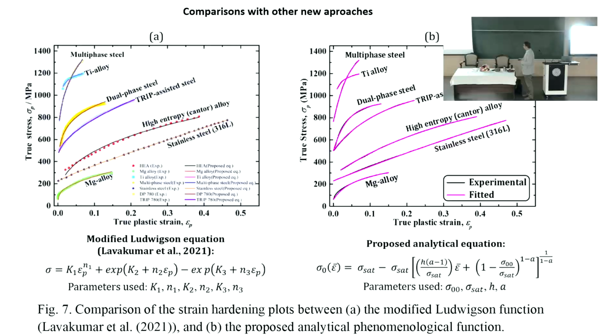You see, here is the function, 1, 2, 3, 4, 6 parameters. 6. We have 4. And one of them is not really a parameter. Let's say 3 and a half. So we did the same and checked. And if you compare carefully one by one, for example, high entropy alloys, definitely much better. You see here deviations. And our agreement is at least as good or better. So this is, again, extremely important. In this way, these authors are happy, because their work is cited, used, and whether it is working less or not is another question.